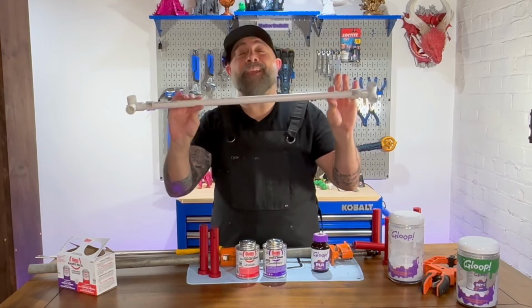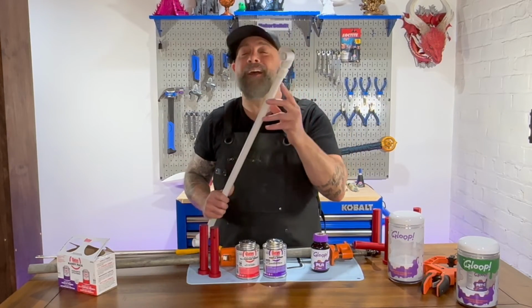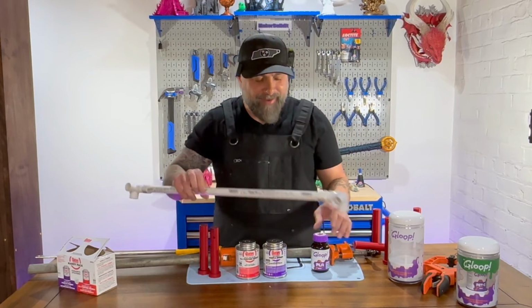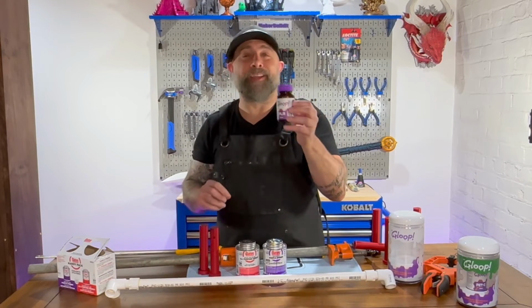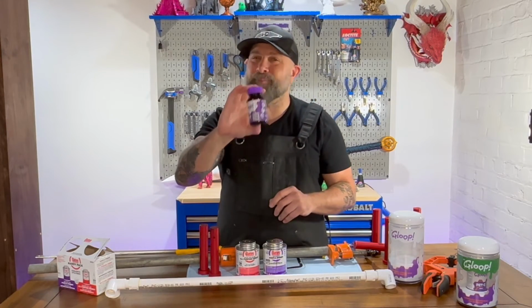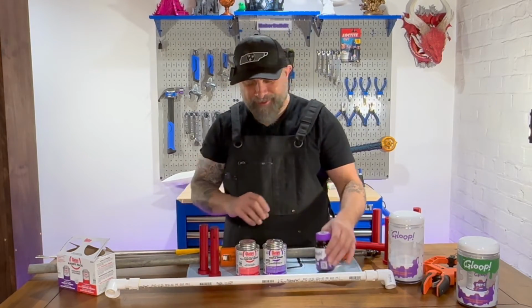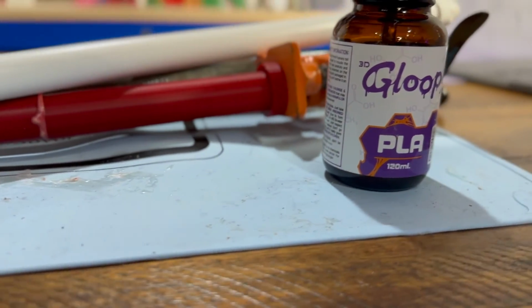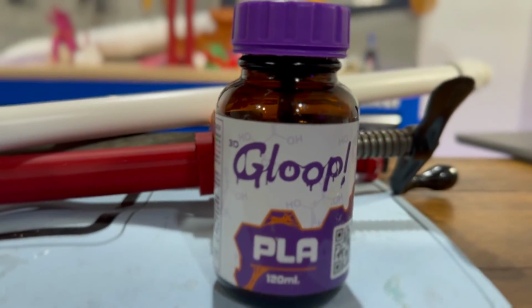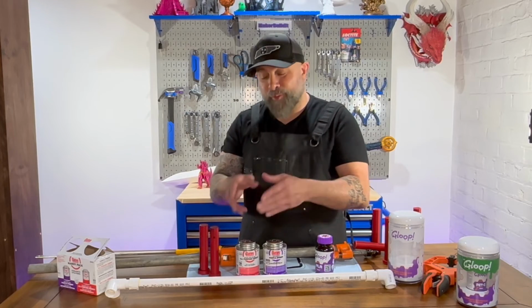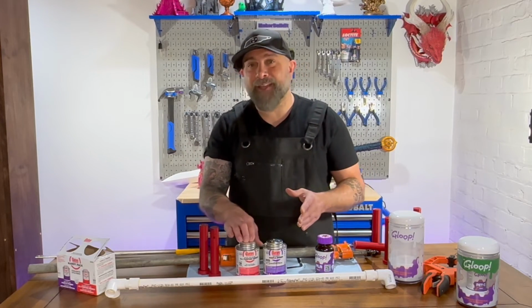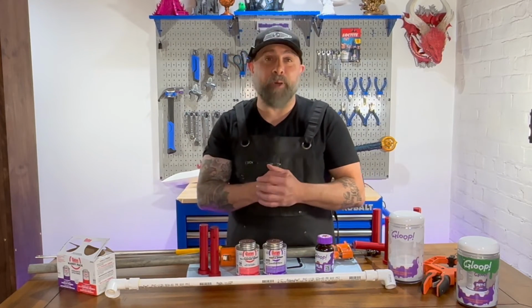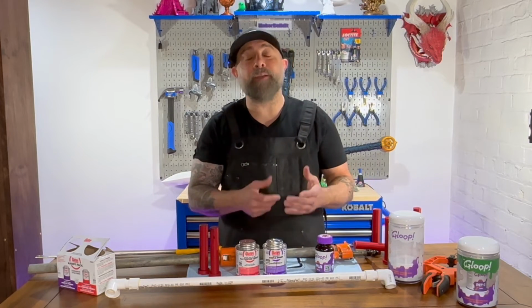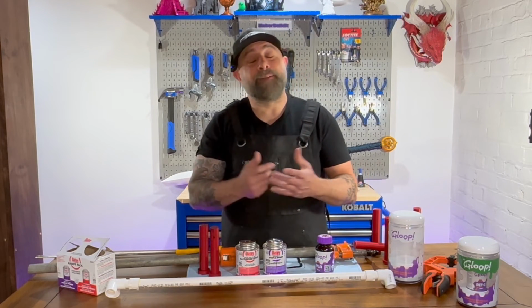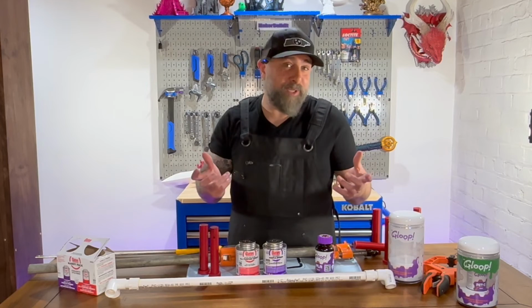Nope, so it seems like the 3D glue could actually hold PVC, but this would be some pretty expensive PVC cement for you to actually use. Obviously, the 3D glue held up much better on the PLA than the PVC cement, even though this was one designed for ABS. Now, I have to say the bond was pretty strong. It did come apart, but it was still a pretty strong bond. Totally feasible to use, it seems.